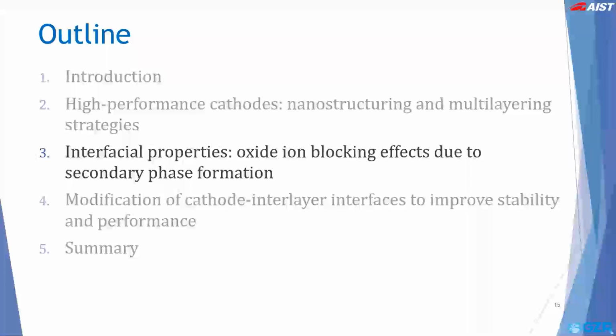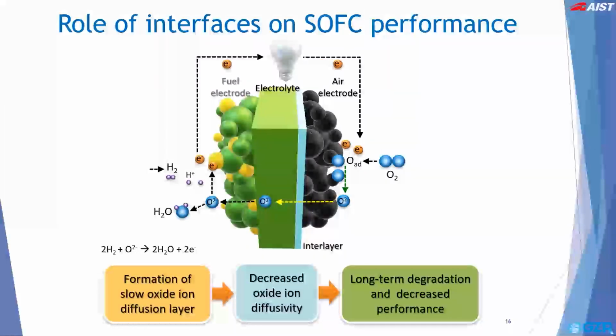The next topic is about the process of transporting oxide ions across heterointerfaces. Ionic transport can be strongly affected by factors such as poor contact, defects, or secondary phases, which arise from cation interdiffusion between adjacent layers. One way to mitigate the formation of secondary phases is to utilize a barrier layer or interlayer to block the cation interdiffusion. Nevertheless, this does not present a 100% solution, and depending on the type and condition of the interlayer utilized at such interfaces, the formation of secondary phases still remains as a major cause of long-term degradation and decreased performance in SOFCs.